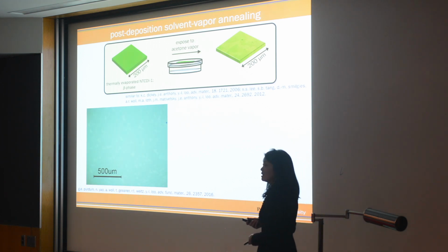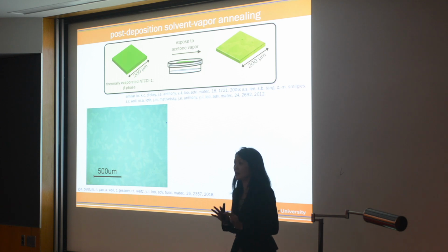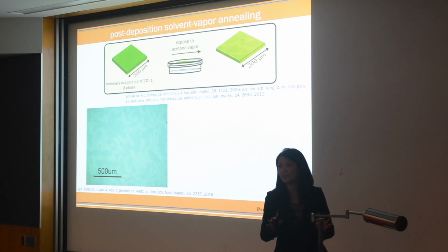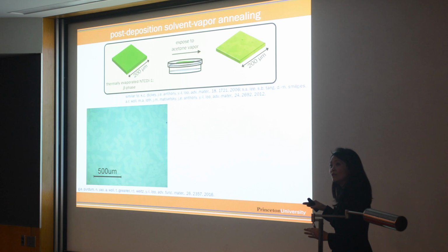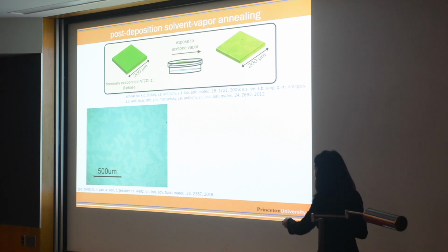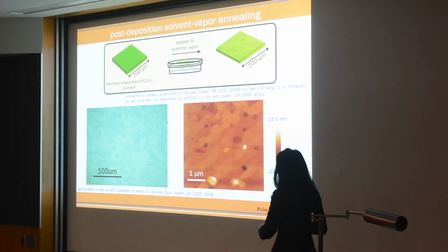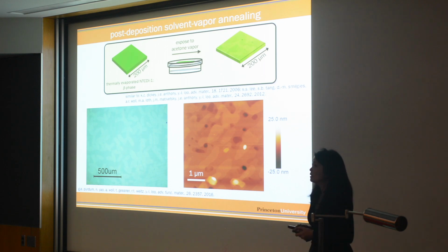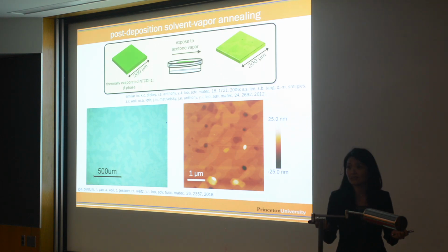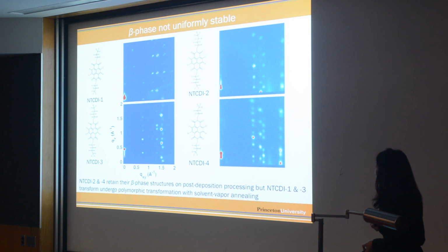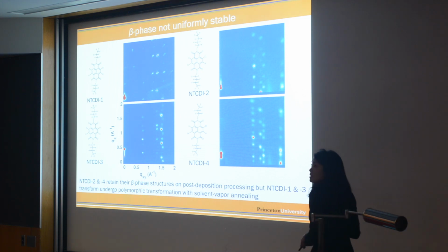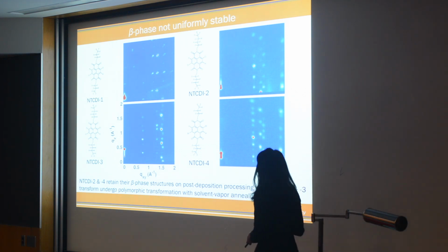And what you can see is a macroscopic change. Now, mind you, the film is already crystalline. So this is a solid-solid phase transformation that we're seeing, right? We're growing big grains here. And this is an AFM micrograph. We can take these films and we can run GIXD here again at CHESS. And so these are the GIXD patterns of the films.